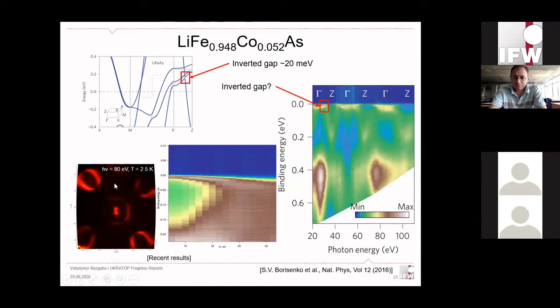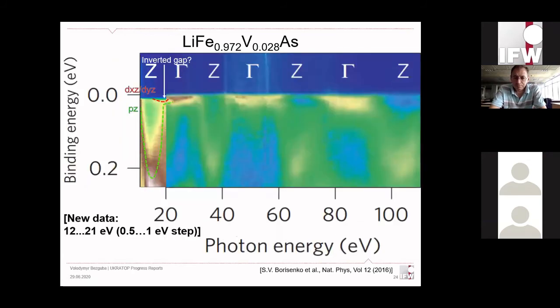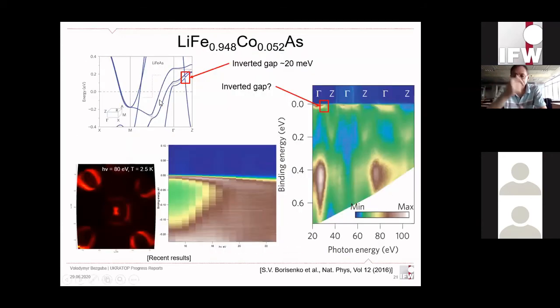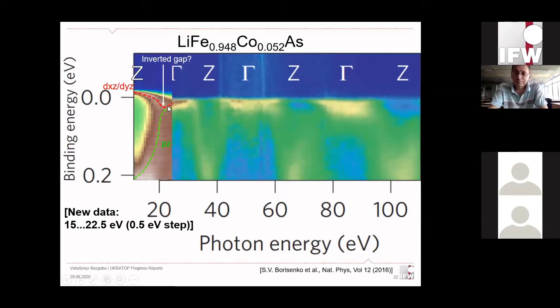But with vanadium doping, there are some changes, though they are very minor, and it's more noticeable on the map when you do the normalization of the spectra so that it looks nicely. Then it's noticeable that the intensities are lower here than in this case. But I think it's just a normalization effect, and the Fermi level changes only slightly.